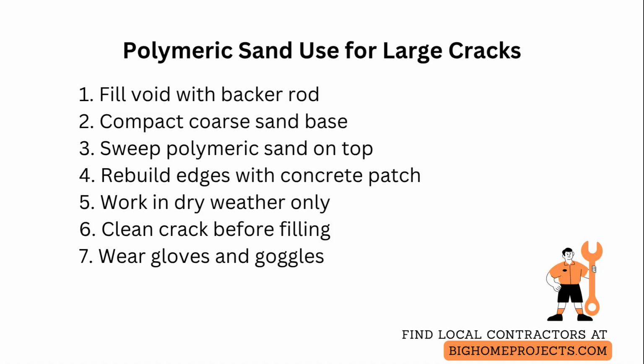After the filler is installed, sweep or pour polymeric sand only into the top portion of the crack up to the manufacturer recommended depth, so the sand can compact and set properly when activated with water. If the crack is extremely deep or the edges are deteriorated, use a concrete patching compound or a cementitious repair mortar to rebuild a sound edge before adding polymeric sand for joint stabilization.